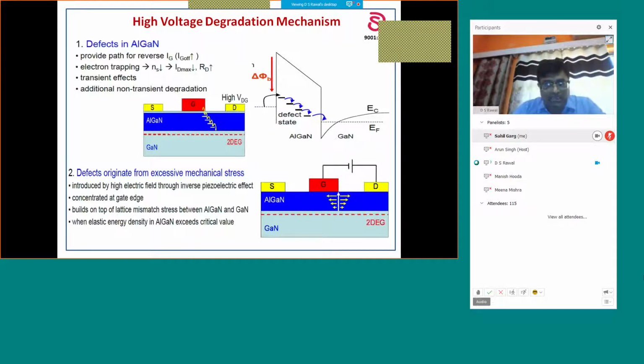But since gallium nitride, aluminum gallium nitride is a defective material and it is a polar material, it suffers from degradation because of the polarization. When we are applying very high voltages, there are chances that it may introduce defects which can cause reliability issues. This is mainly because of lattice mismatch. These defects originate mainly because of excessive mechanical stress by application of high voltage. This is called the inverse piezoelectric effect.